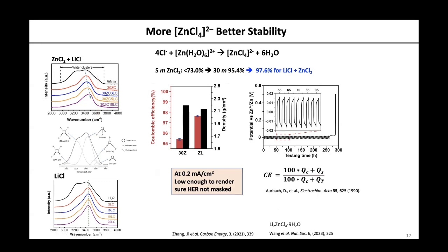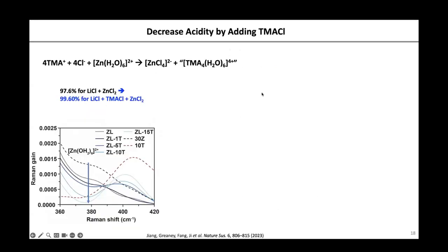Now we notice that you can make the electrolyte more stable by adding chloride. How about doing that with a soft cation, tetramethylammonium? A soft cation will not polarize the water as much, so that could reduce the acidity. So now we are talking about acidity reduction. Again, this reaction is going to be very similar. We have a new salt added. It's going to deprive zinc of water and turn zinc into more zinc chloro species. And now the hydrated cation is replaced by TMA instead of zinc. So this will not polarize water molecules. It will be less acidic.